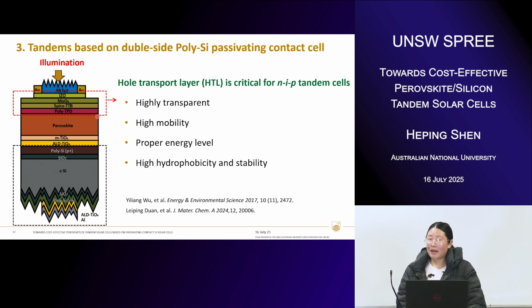In this NIP cell structure, there is a long-lasting challenge, particularly related to the HTL side, which is on top of the perovskite, a layer that is used for hole transport. There are a few criteria we need to meet for an efficient hole transport material. First, it needs to be highly transparent to allow minimum perovskite absorption loss. It has to be very conductive to allow good performance. It has to provide favorable energy levels. It has to be stable. So we were trying to find a material that can meet all of these criteria.